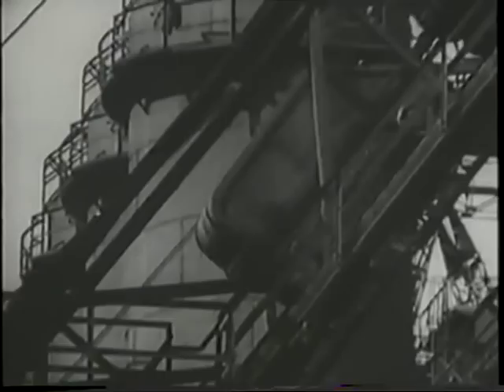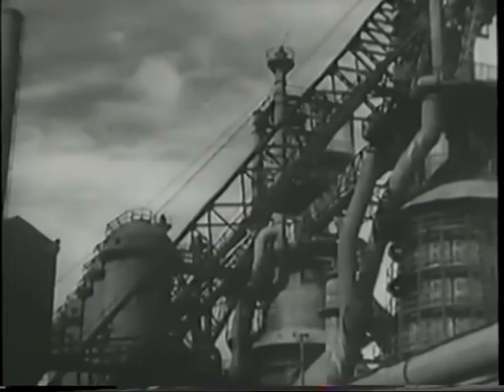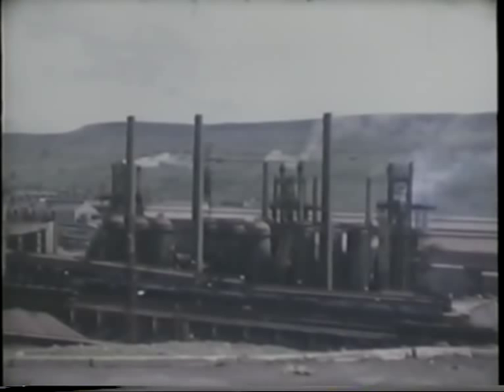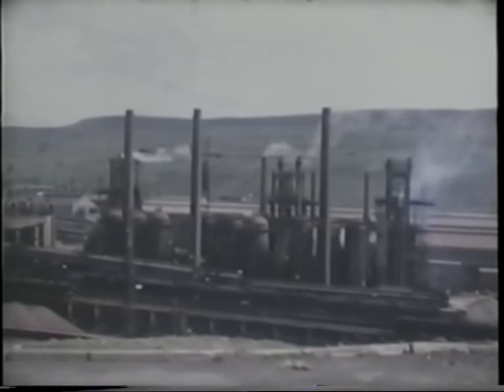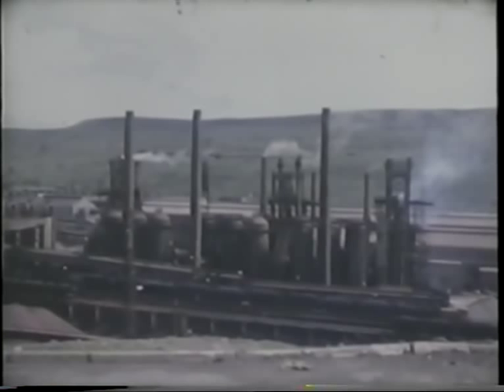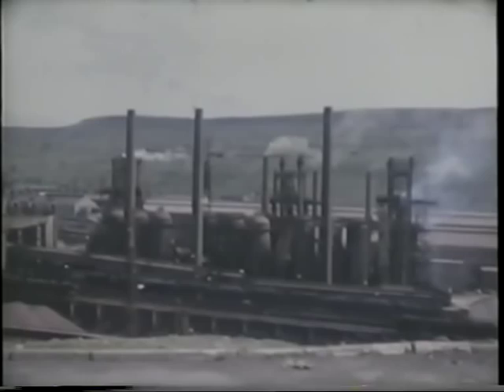Blast furnaces extracted iron from ore by heat and combustion of gases given off by the coke. Ebbw Vale's furnaces were fed continuously with iron ore, coke and limestone, to be tapped at 4 hour intervals. The blast came from three turbo blowers, each of which produced up to 50,000 cubic feet a minute at 30 pounds pressure. Air was passed through separate heating stoves. Hot blast meant higher production, and Ebbw Vale's would rise to 350,000 tons each year. Inside the furnace, temperatures could reach 2,000 degrees centigrade. In their later period, these furnaces were injected with oil, which was found to increase yields.